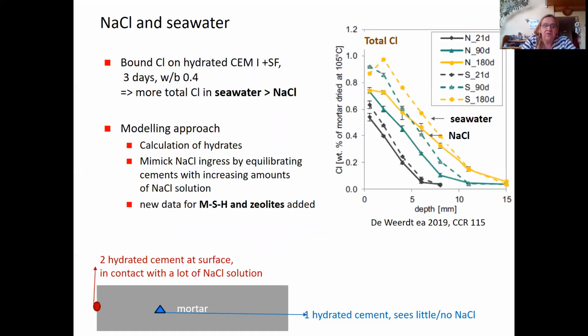The second example is the effect of sodium chloride and seawater on hydrated cements. And here, this is measured chloride ingress after 3 weeks, 3 months, and half a year. And we can see with time, we have a higher and higher ingress of chloride in the sample, and there's some difference between seawater and sodium chloride.